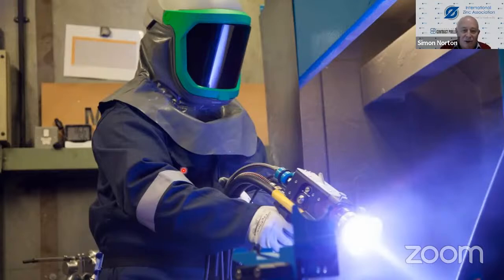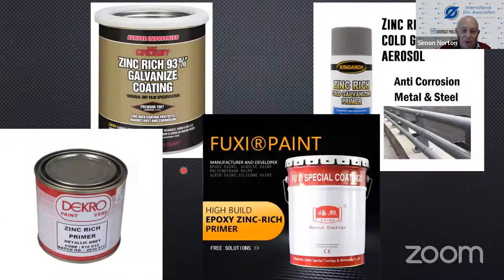And then later on, these are a variety of zinc-rich paints. And you can see the variety that's offered. And I must tell you, if you look at the top right-hand photograph, zinc-rich paints are not cold galvanizing. When you galvanize steel, you form a range of iron-zinc alloys, and there's a metallurgical bond between the galvanizing and the steel. When you use zinc-rich paints, it's by adhesion and mechanical adhesion. But Graham will talk about that in a minute.